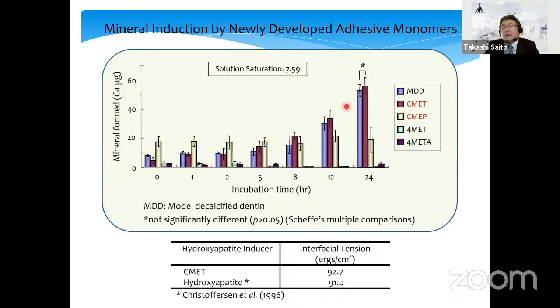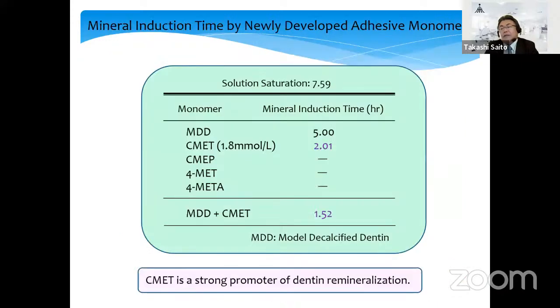The CMET induced mineral formation the same as the model decalcified dentin, but 4-MET and 4-META did not induce mineral formation. The interfacial tension of CMET for hydroxyapatite nucleation, which is a good indicator of mineral nucleation ability, is a good value for hydroxyapatite nucleation compared to hydroxyapatite seeding.